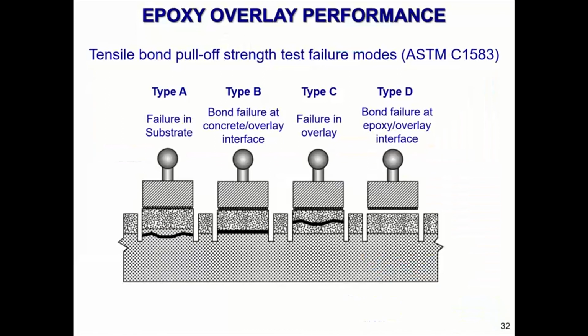Here's a little detail on the different failure modes you can have in a tensile pull-off strength test for thin epoxy overlays. Type A is what you're looking for. It's where the epoxy does not fail, the bond does not fail. What it does is it fails the concrete. Type B failure is a bond failure between the concrete and the overlay interface. A type C failure is a failure in the overlay. You have 2 layers of thin epoxy overlay, and you don't want a failure in the overlay. And then type D is a bond failure between your testing machine and the epoxy.